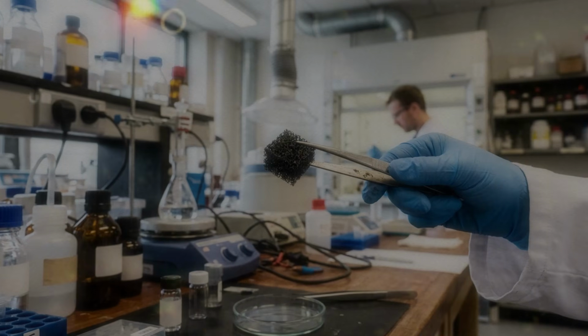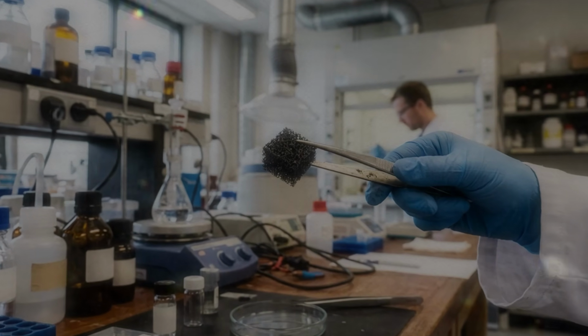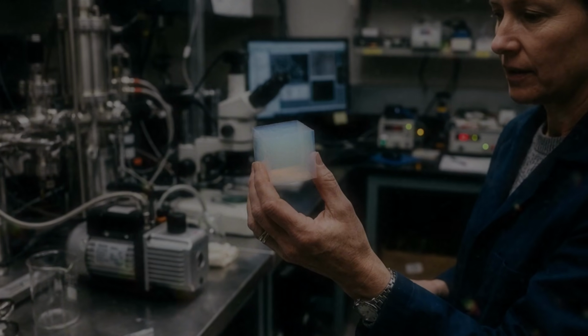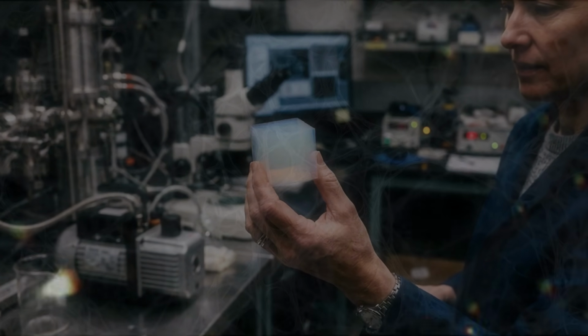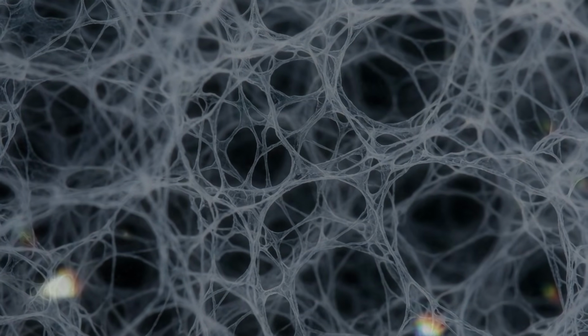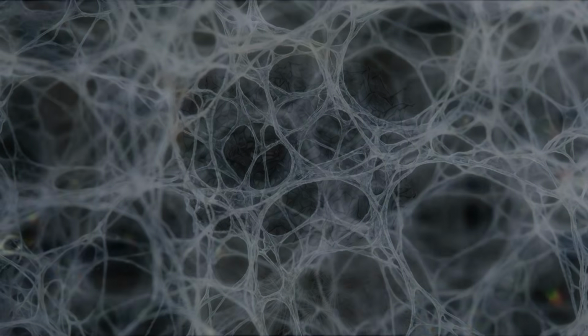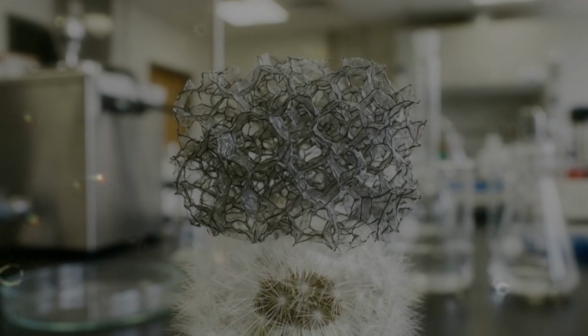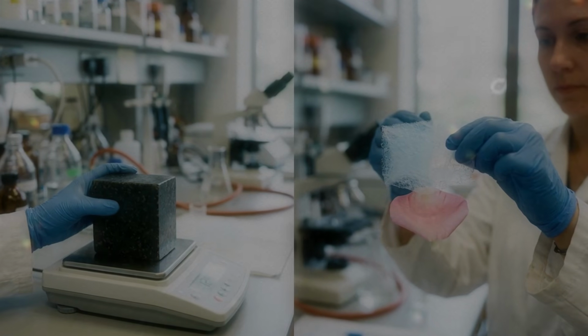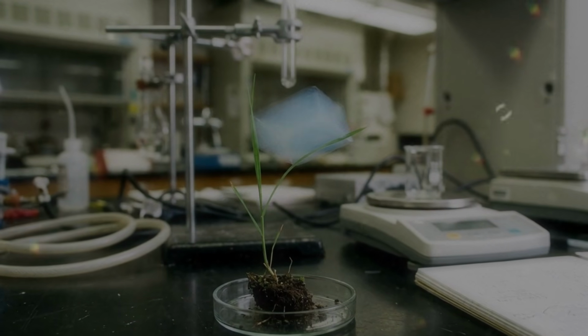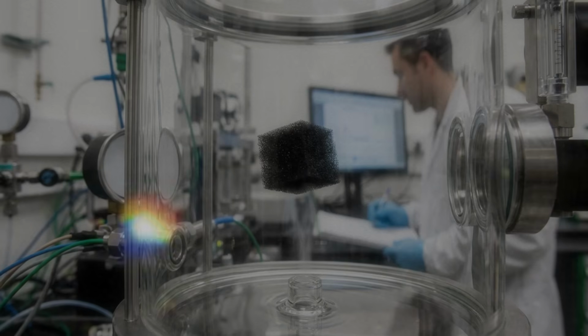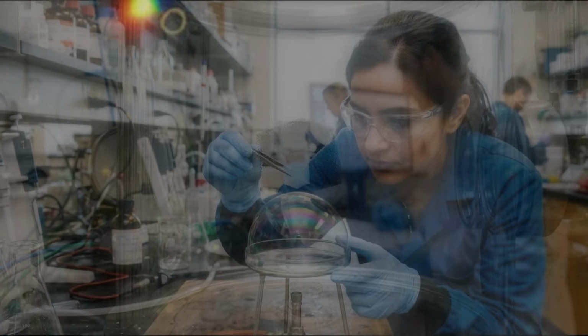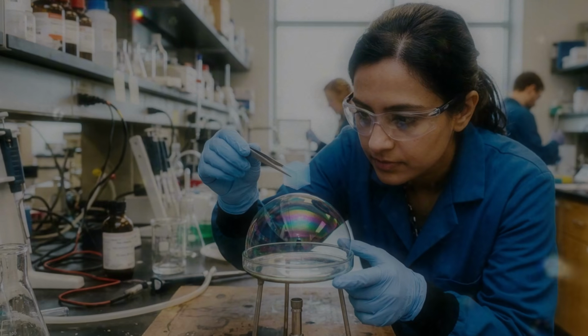Oil viscosity also matters. A light fuel moves into pores more easily than heavy crude oil. Cold oil can become thick and slow. Researchers have explored using the dark carbon framework as a heater. Sunlight or electrical current warms the aerogel and the nearby oil, reducing its viscosity so it can enter and leave more easily. Magnetic particles can be added so the oil-filled aerogel can be guided or collected with a magnetic field. Reinforcing sponges can improve durability. Surface treatments can increase water repellence. Every improvement adds material and processing. A magnetic, reinforced, electrically heated graphene aerogel is no longer the simplest or lightest version. It may still be useful if the added functions solve the practical problems of a real spill.